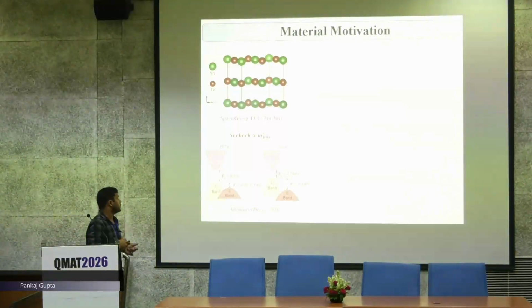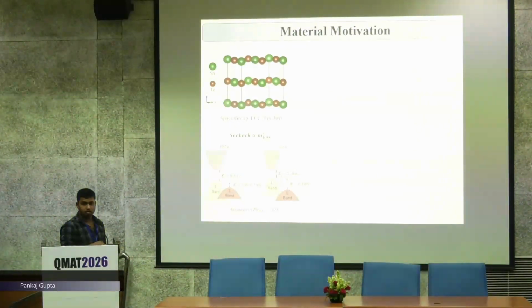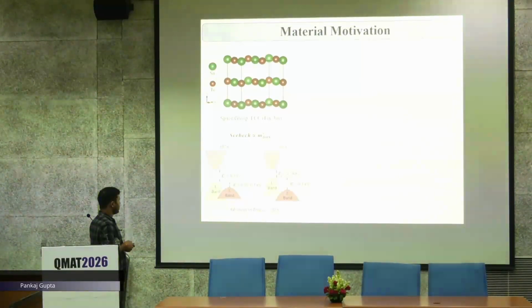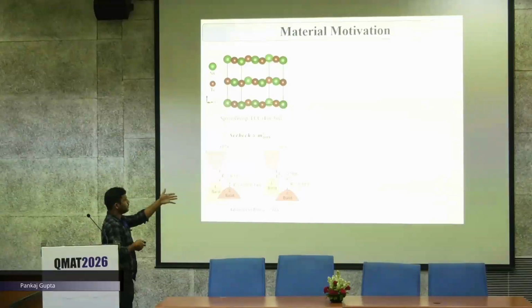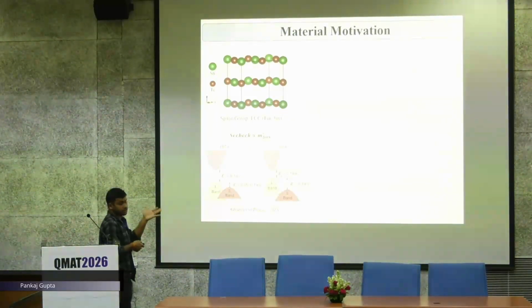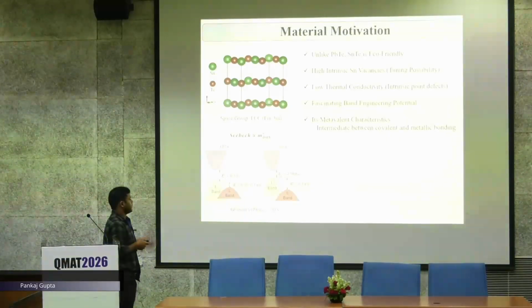So why did I choose SnTe? Previously people have explored a lot about the excellent thermoelectric properties of PbTe, and PbTe and SnTe have the same structure. Even so, SnTe does not have good thermoelectric properties. The reason behind that is these numbers. This delta is the band offset between the light hole and heavy hole bands. If this band offset is very low, this band also contributes to transport, and hence the density of states and the density of states effective mass will be very high, and this will give a higher Seebeck coefficient. But in the case of SnTe, there is a very high band offset that is limiting its Seebeck effect, and hence it has been a problem.